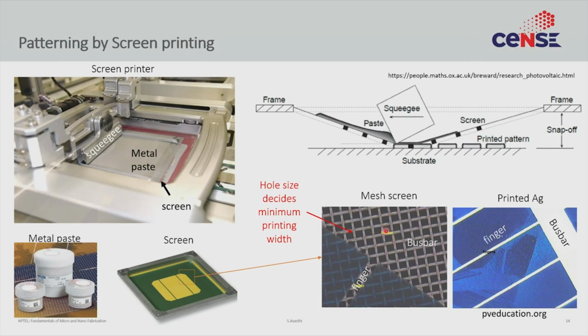And while we keep pushing the technology, the current state of the art is that you cannot print reliably below 20-30 microns. Most commercial Indian manufacturers that I know of tend to print somewhere between 30 to 60 microns. Okay, so that's the thinnest they can make. These are fingers, as they are called. This is the thinnest line you can make. This is the critical dimension of your printing.